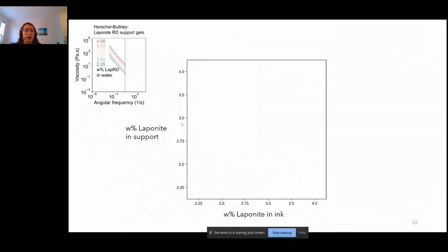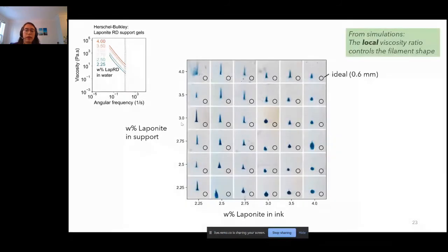So now let's look at our experimental fluids. So here, our local viscosities are going to change, and they're going to increase as we increase the concentration of laponite in the material. So here we're printing laponite water into laponite water, but our ink has a little bit of dye, so we can see contrast. So if you look at the bottom right corner of this plot, you can see that as we go to high ink viscosities and low support viscosities, we get circular filaments. If we go towards the top left corner of this plot, where we have low ink viscosities and high support viscosities, we get very tall and narrow filaments. And these filaments also get sort of sharp edges at the top and at the bottom of the sides.